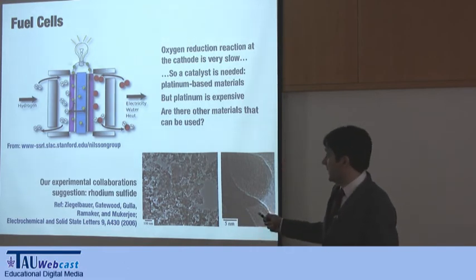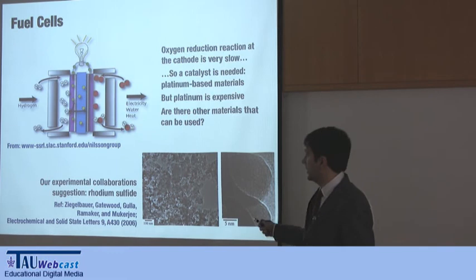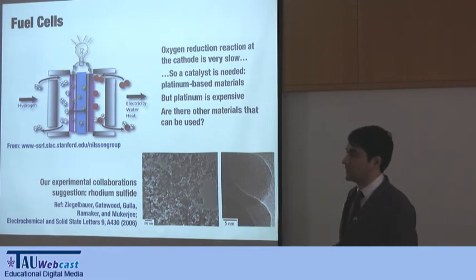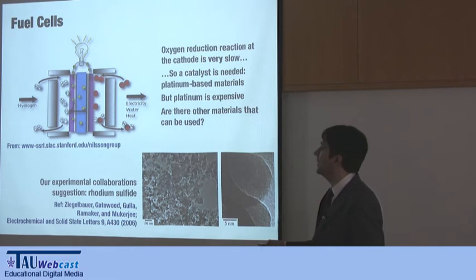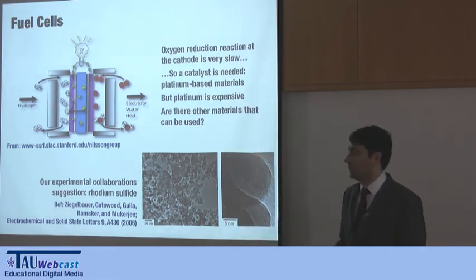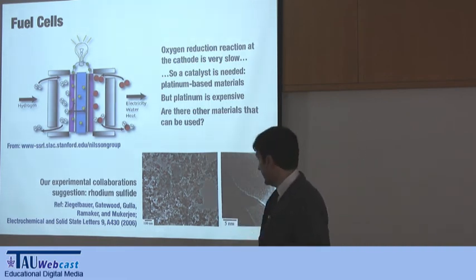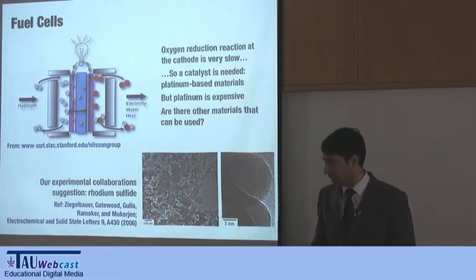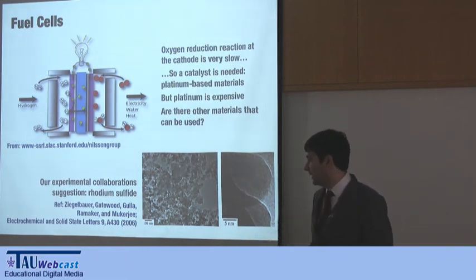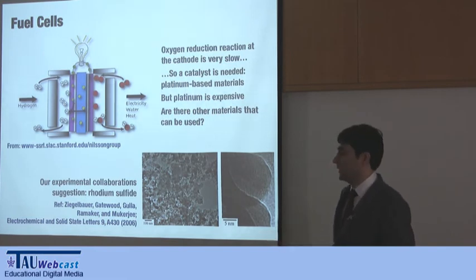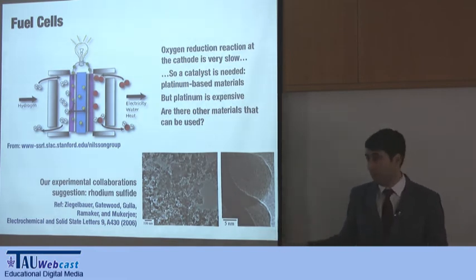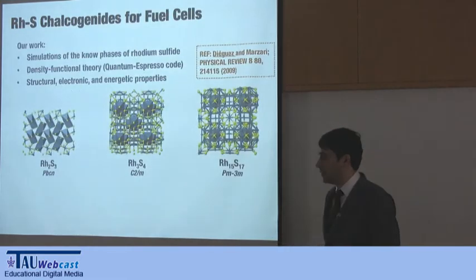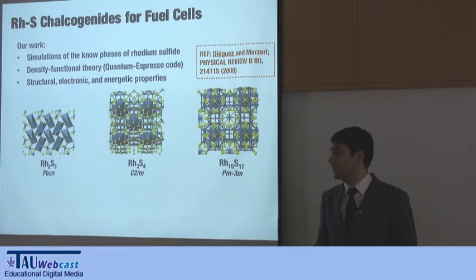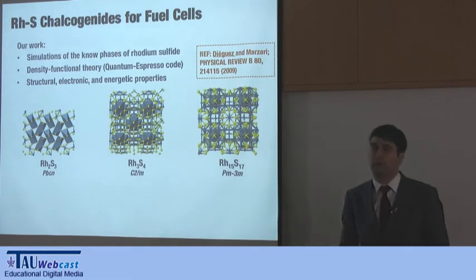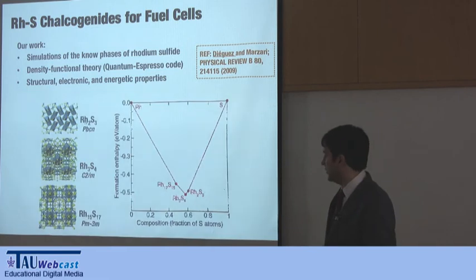The problem with this is that this recombination, this oxygen reduction reaction, is very slow. So you need a catalyst. The most used catalyst is platinum or platinum-based materials, but it's very expensive. Can you use something else? There was a group at the time, an experimental group, collaborating with the group I was in MIT, and they wanted to study rhodium sulfide materials that are, well, but by now they are commercializing. At the time, basically nothing was known about this material, so we did a very preliminary exploration of its main properties. I'm not going to talk about them.